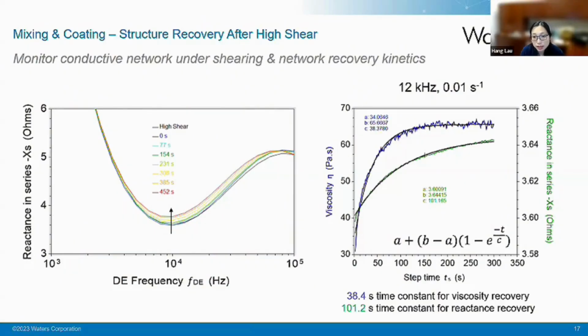And you're picking for those; that's one example showing here. For the slurry after the recovery, you're seeing the viscosity recover pretty rapidly, maybe around 38 seconds, and it already gets back to the original viscosity. However, the conductive network, which we're monitoring with the real impedance, did not recover to what it was supposed to be until almost over a minute. So when you're thinking about putting in your slurry coating, how long the distance is between that and the drying oven to lock it in place, you need to understand how much time you have to lock in. If you lock in too early or too late, you will change the structure as well.